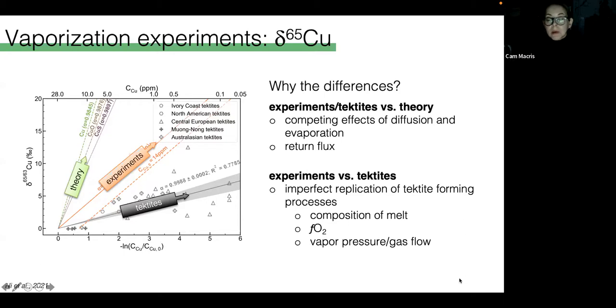If we also try to think about what might be behind the difference between our experimental alpha and the natural tektites, so what's up with the difference between these two trends here, we're going to immediately consider that we are imperfectly replicating the tektite formation process. So firstly, the melt composition in our experiments is more mafic than tektites. Secondly, we are likely not replicating the FO2 of an impact plume with the argon gas as our atmosphere.